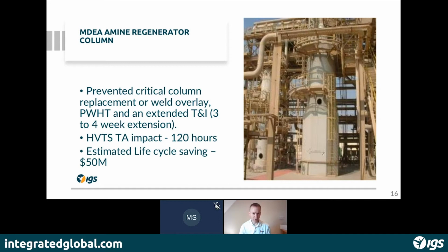The first thing they had to do was a fitness for service inspection to make sure the column was still fit for service, safe to operate. It passed, but what it did demonstrate was that in many locations around this middle section of the column, they'd lost the majority of their corrosion allowance and were right on the minimum in terms of their remaining steel. So they had to install a system that was going to stop any further corrosion and freeze the condition of the metal. They looked at doing a weld overlay service in this application area.